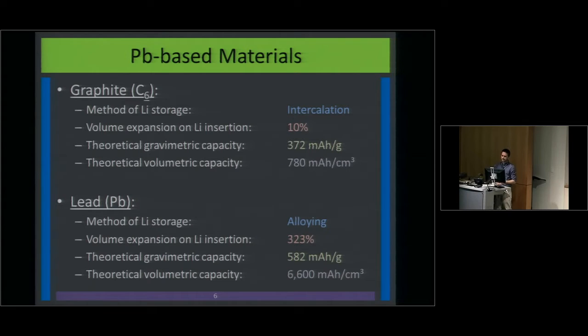Lead has a completely different method of lithium storage. It actually alloys with the lithium, basically forming chemical bonds and creating a whole new crystal structure. This means it can take up a lot more lithium. You can get 4.5 lithiums per atom of lead, whereas only 1 atom per 6 atoms of carbon for graphite.